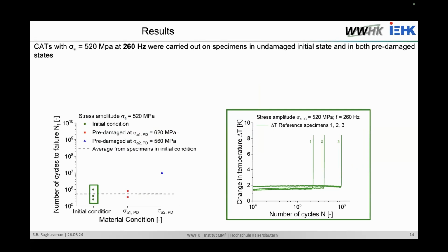Now we are going to move on to the secondary loading. It is done here at 520 megapascals at 260 hertz, and it is carried out on initial condition specimens as well as pre-damaged specimens, to have a reference. Here we have the graph where we see the number of cycles plotted against the material condition. The green dots represent the specimens in initial condition without any pre-damage at all. The second set, with the red rectangles, shows the pre-damaged specimens at 620 megapascals, and the third one is the pre-damaged specimens at 560 megapascals. Here we see the cyclic deformation curves for each condition. This one is for the initial condition specimens.